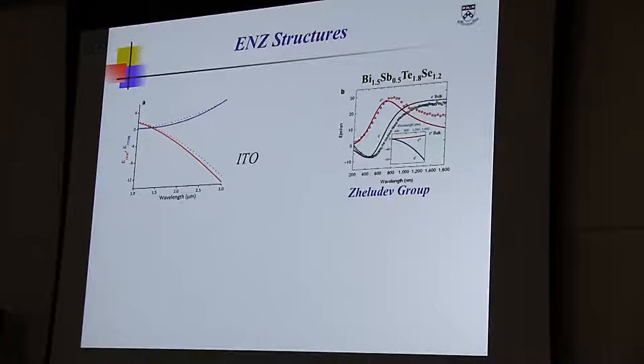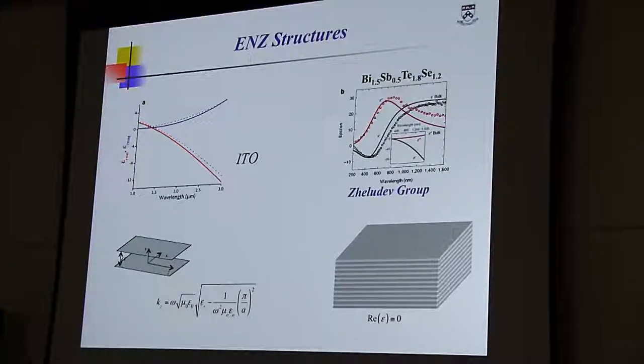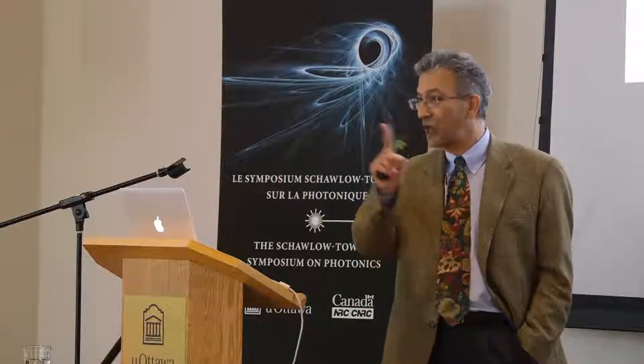But if you don't like any one of these frequency domains, you want to make the epsilon near zero material in the frequency you like, then the concept of metamaterial will help us to put a stack of these layers together with epsilon positive, epsilon negative, to actually engineer epsilon near zero material. And finally, those of you who are interested in microwave, there's another interesting and easy way to create an imitation of epsilon near zero, and that is just pick up a simple parallel plate microwave waveguide, and operate it with the TE10 mode at its cutoff frequency. You do that, you get epsilon near zero effective properties. Because the dispersion of a TE10 mode follows this formula, and this formula is exactly the Drude model, but not with the electron density.